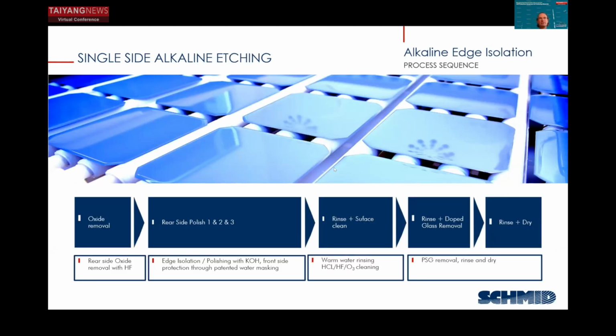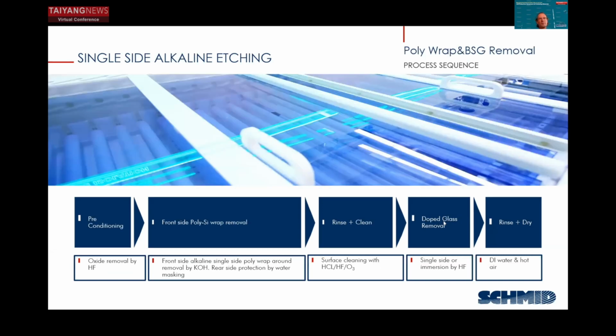Then we have the alkaline edge isolation system in our portfolio, where you start with an inline single side oxide removal to access the rear side for polishing. Then you do a bath with KOH, again at elevated temperatures, for the rear side polishing. Then you do rinse and surface clean. Then you can do a rinse and dope glass removal, or you just leave the glass on. That depends on your process.